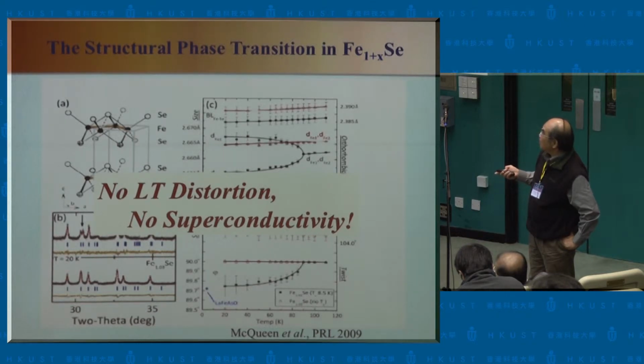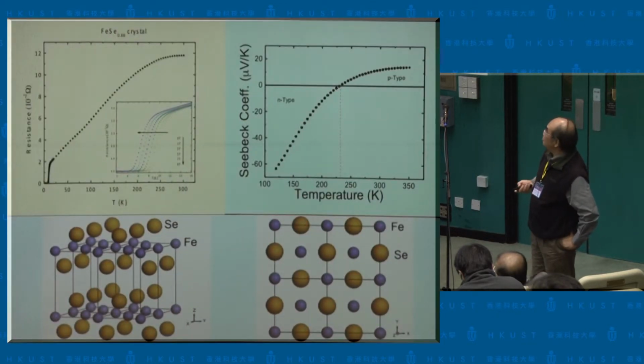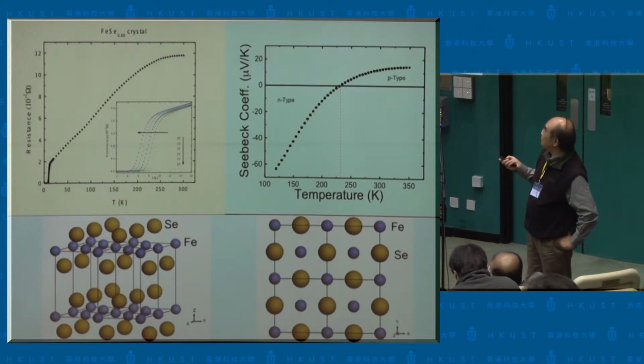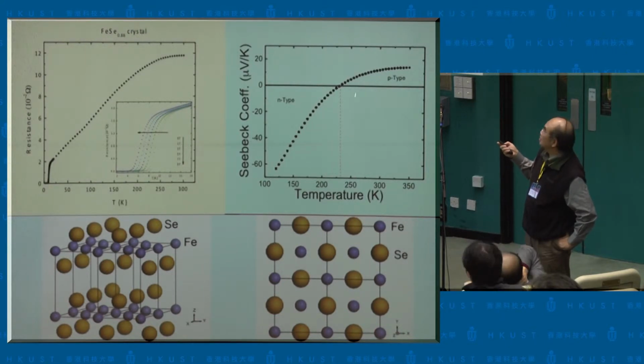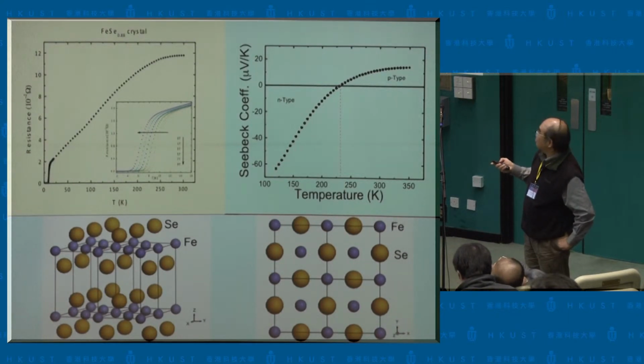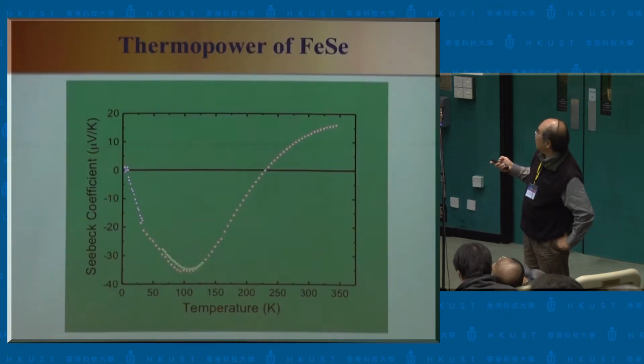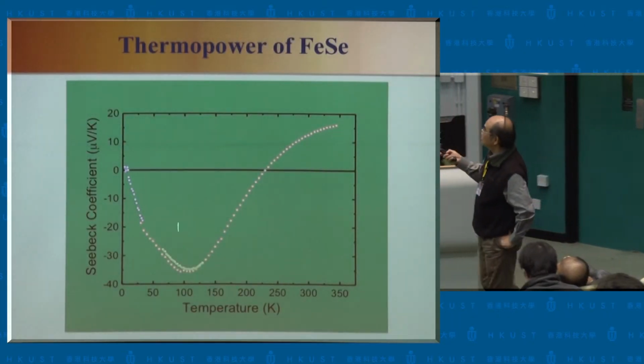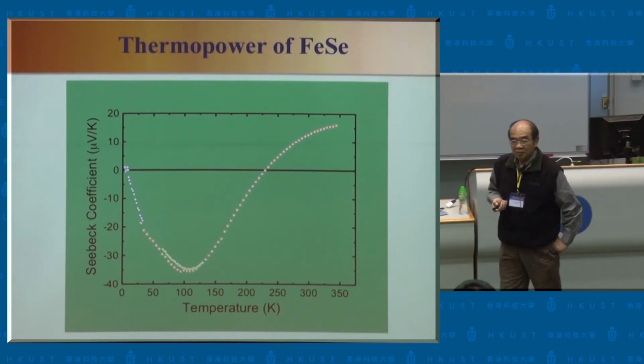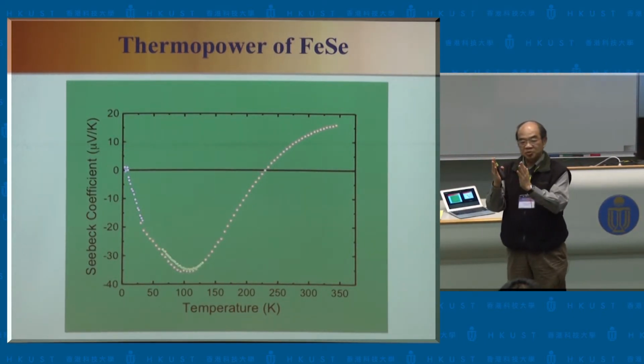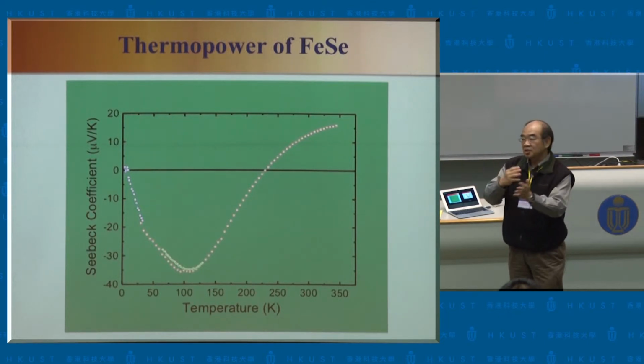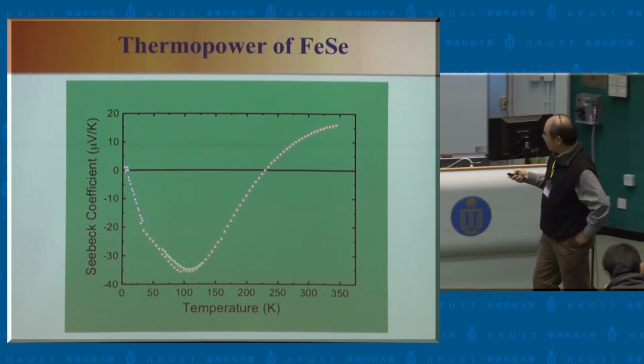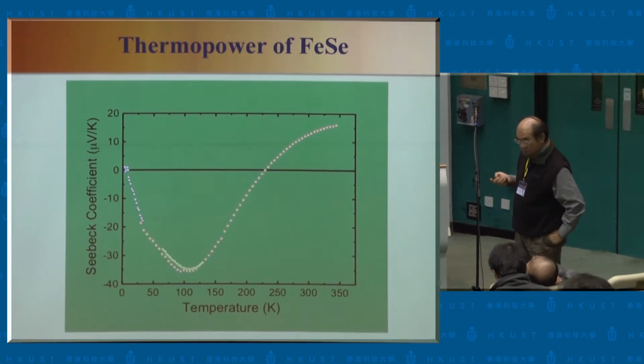Okay. Now let's look at the other feature. For example, there's a thermoelectric effect. When you cool down, first you see one signal here around 220K, the crossover from P to N. And more interesting is that when you cool down to low temperature, there's a local maximum around 100 Kelvin, which is the distortion temperature. So there is some kind of electronic variation we associate with this structural distortion.